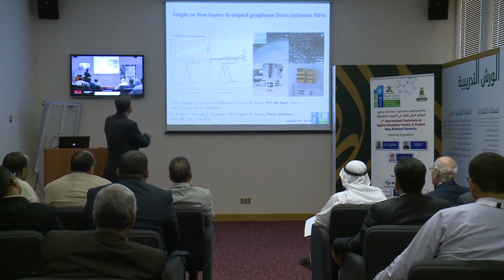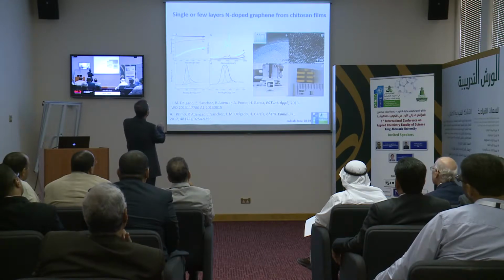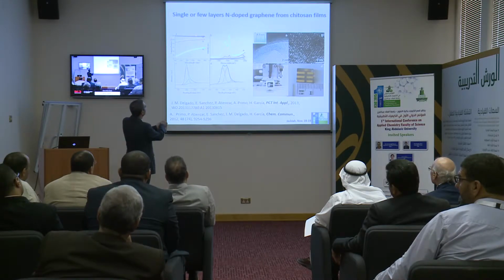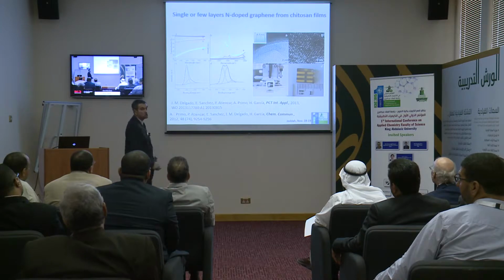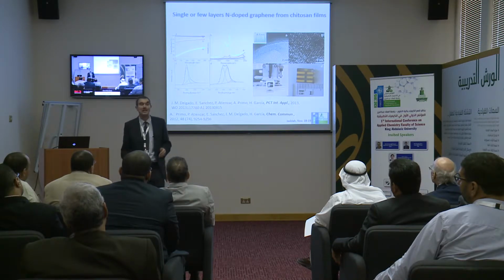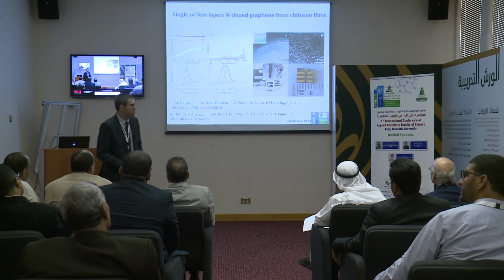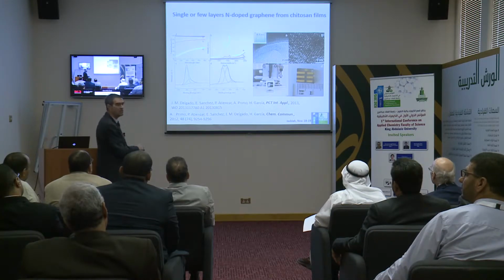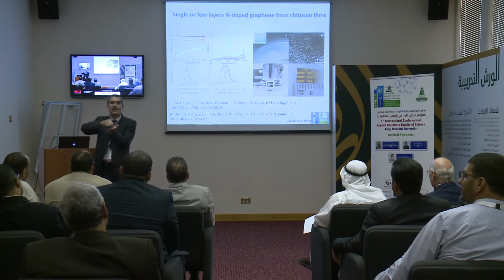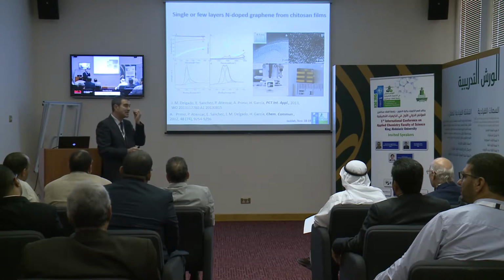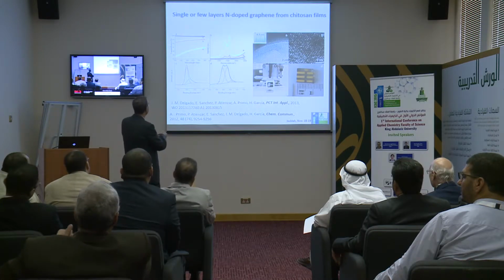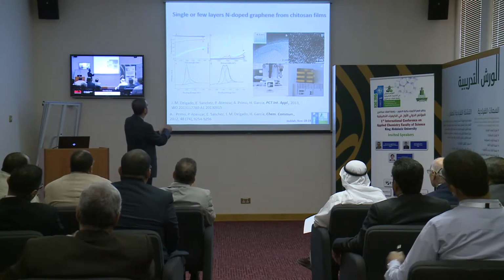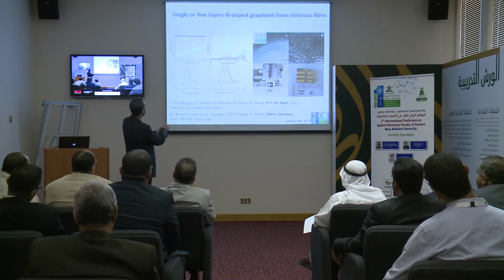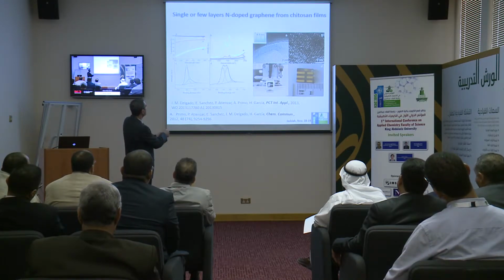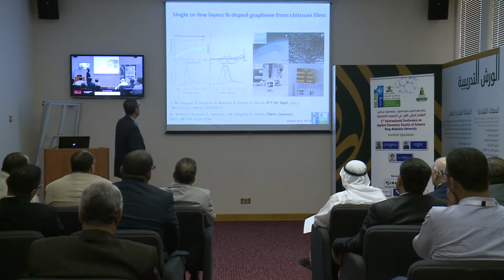So in a film, one characteristic of graphene is that graphene is very transparent. So this scale is transmittance of light, and this is 100. Have a look at this, because single-layer graphene has a transparency of 99%. So all the light goes through, so the eye cannot see anything. But as soon as you have 2 layers, because there is pi-pi interaction between the layers, then the eyes start to see something, and it's because the light is not totally transmitted. So now we have about 95% transmittance in the whole range of UV and visible wavelengths.